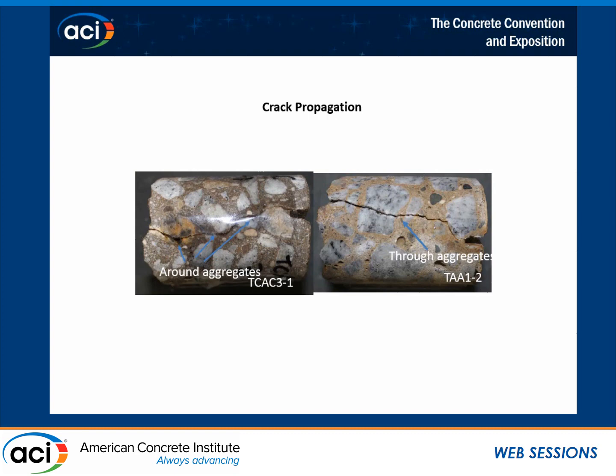Now we have another one, that calcium aluminate cement. It had some cement in it. I don't have that data available because we just took those samples out, but that did not do that, and we suspect that's going to look a little bit more like the OPC as far as behavior.